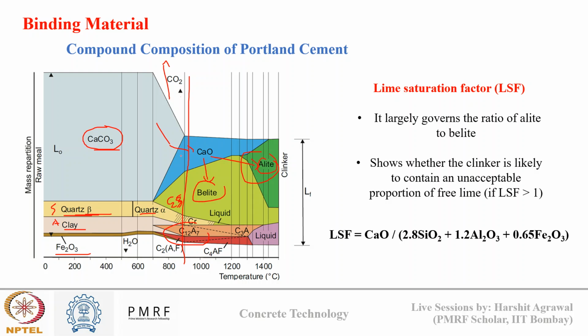So till now, till 900 degrees Celsius, what was happening? All the CO2 was liberated, and silica oxide, alumina oxides, and CaO all formed. Now they have started blending into final solid solutions like alite, belite, calcium aluminate, ferrite, all these phases start to form, from beyond 900 degrees Celsius till 1500 degrees Celsius.